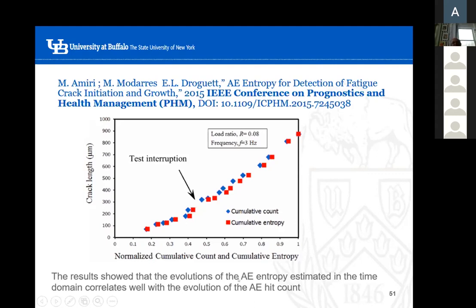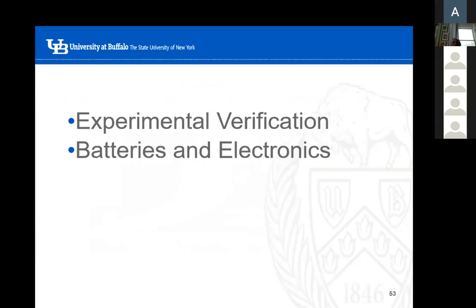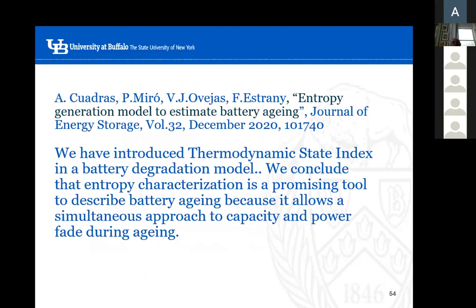And then the results show that the evolution of the entropy estimate in the time domain correlates well with the evolution of AE hit count. AE stands for acoustic emission. People also applied this to batteries. And this is a group from Spain. They published the paper in Journal of Energy Storage. We have introduced a thermodynamic state index in a battery degradation model. We conclude that entropy characterization is a promising tool to describe battery aging because it allows a simultaneous approach to capacity and power fade during aging.